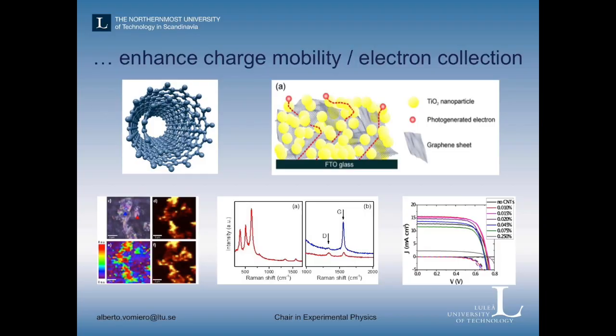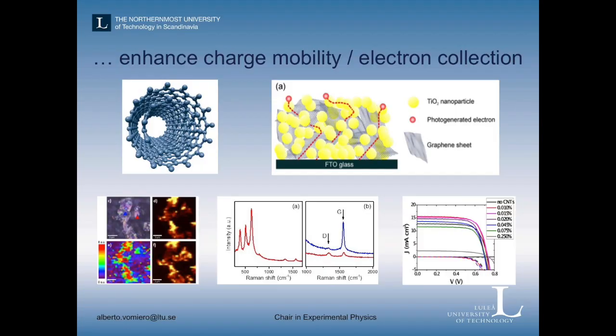Graphene, which was awarded with a Nobel Prize in 2010, and the professor who was the chair of Nobel Prize in that year now is guest professor at LTU is Ingemar Lundström, so we're very honored at that. Graphene is a single layer of carbon atom which are distributed orderly in an hexagonal pattern, and the conductivity can be much higher than composite materials or mesoporous films. So we tried to put together these graphene sheets and titanium oxide particles, and we demonstrated that it's very useful to increase the photoconversion efficiency.